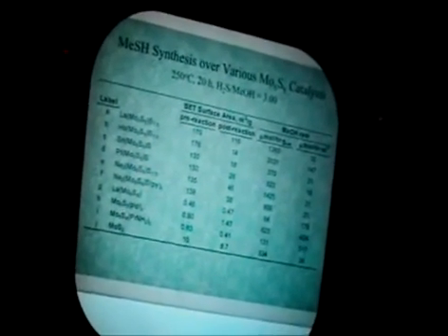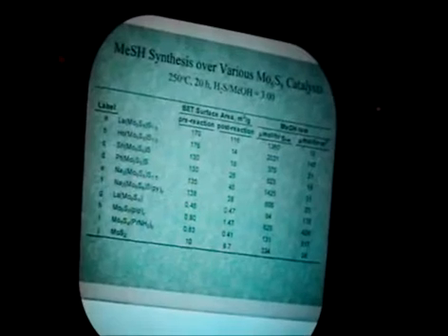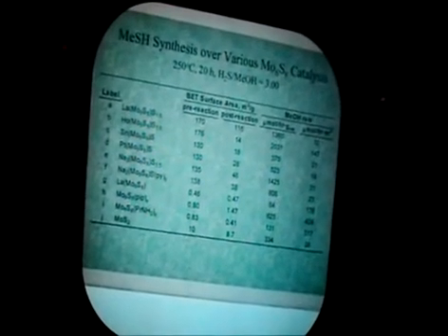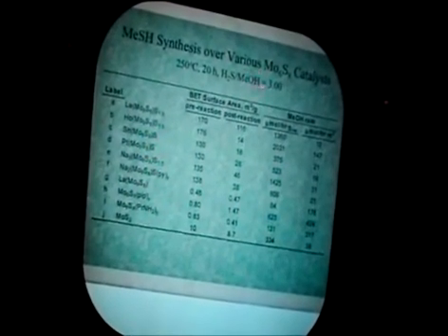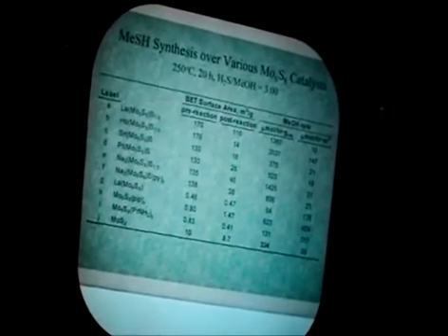First of all, we notice that the reaction is at 250 degrees C, which is fairly low compared to commercial applications of thiol synthesis catalysts, with a fairly low hydrogen sulfide to methanol ratio. But even at 250 degrees C, we're losing quite a bit of the surface area that we have to start with in the reaction.